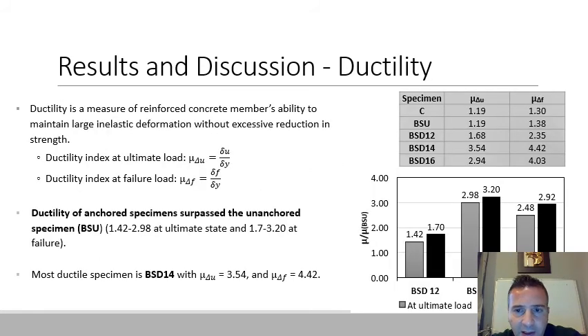And this is in terms of ductility. You can see that the 14 millimeter behaved the best in terms of ductility, 3 times more than the control specimen, because this is shear, and even more than that of the unanchored specimen. So very interestingly, anchoring the sheets with splay anchors will enhance both the strength and, most importantly, the ductility of the member, and most likely is going to give you an indication of failure. So basically the beam is going to fail in a ductile mode rather than in a brittle and sudden mode.